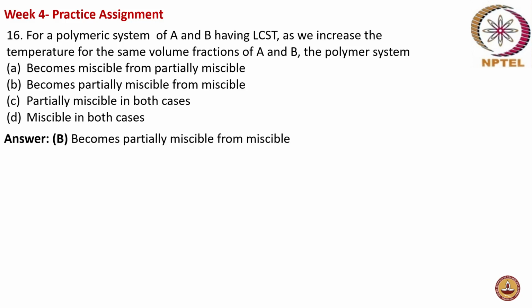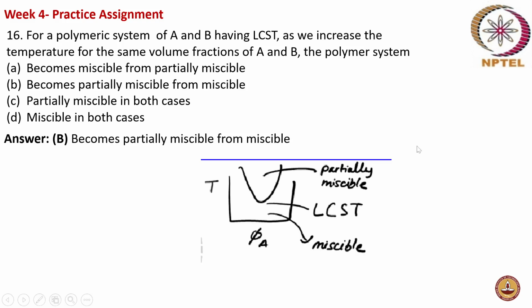Okay, it actually becomes partially miscible from a miscible system. If you look at this, this is temperature versus volume fraction. Below the lower critical solution temperature, the system is completely miscible. For a particular volume fraction, say 0.5, if you start from the lower critical solution temperature and keep increasing the temperature, it becomes a partially miscible system. From a miscible system it gets converted to a partially miscible system.